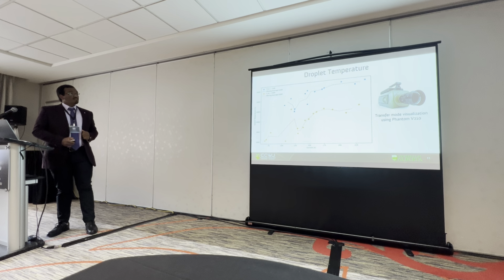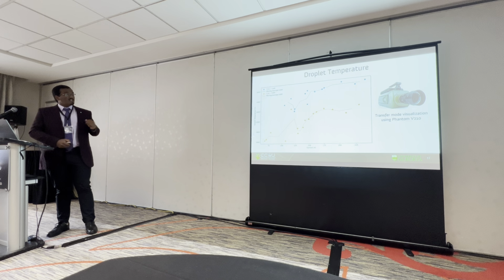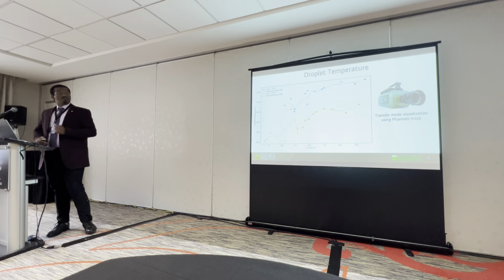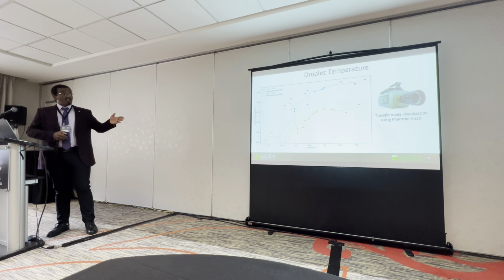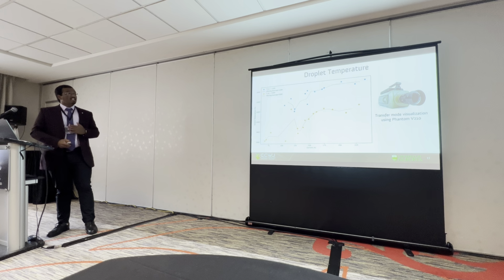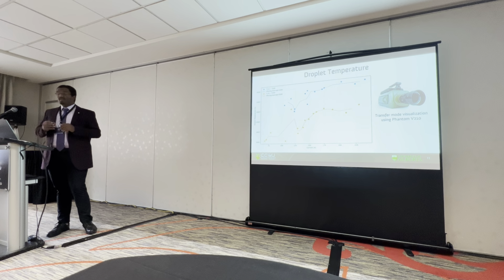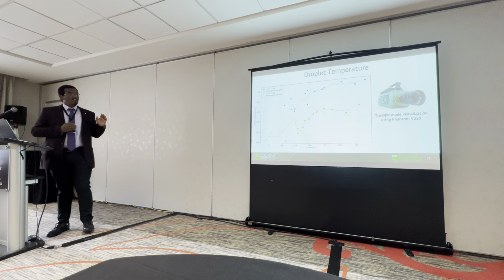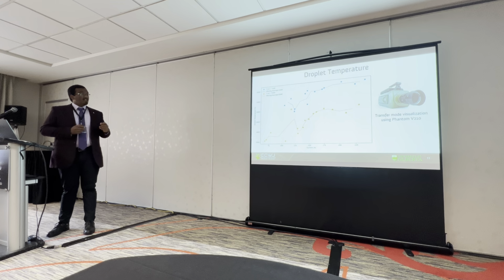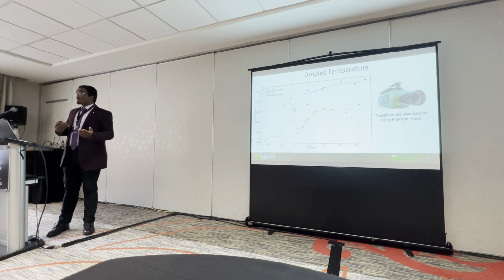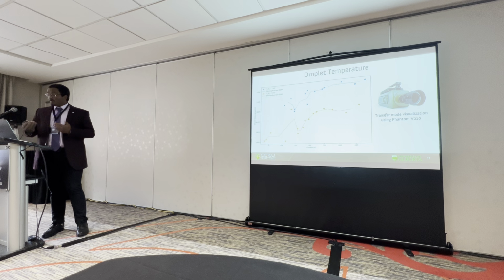The ones marked in blue squares are 1100, and the ones marked in orange triangles are 5183. I have a moving average of 2 points trend line so that we can understand the trend as a whole. You could see that the 1100 alloy, which is just pure aluminum, tends to have a much higher droplet temperature across the entire current range. And the difference is not even small. It ranges from around 200 degrees Celsius to around 400, 500 degrees Celsius over here. So you could say they both have a pretty solid difference.